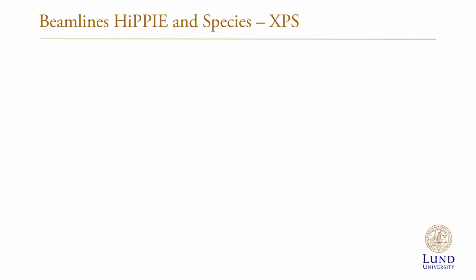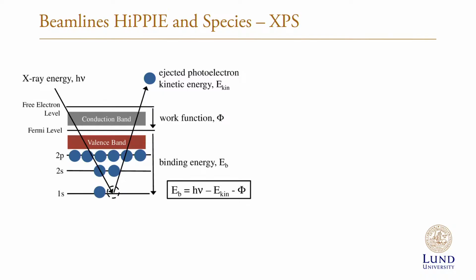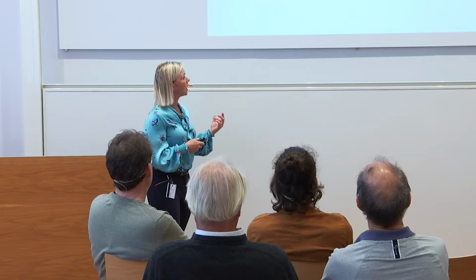However, there are two beam lines that we have been using. They are called HIPPIE and SPECIES, and the technique that I just told you about is called X-ray photoelectron spectroscopy, or XPS. In this case, the X-rays from the synchrotron knock out one of the electrons, which is the photoelectron, and we can measure the energy of this electron. And that carries a lot of information to us about the material that it comes from.